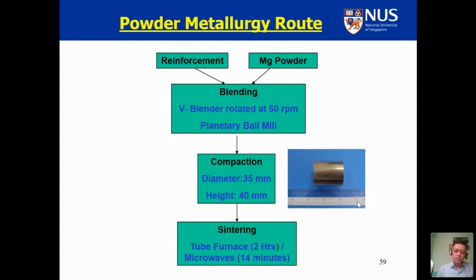Then the people also in the material industry make the material using the powder metallurgy method, in which, if they want to make an alloy, they put one powder with another powder. If they want to make a composite, they add the magnesium powder with the reinforcement, blend it using either a V blender or planetary ball mill, compact it into a billet like the one shown here, and then you can sinter it. Traditionally, people are using the conventional furnaces to sinter the material, which is a time consuming step.